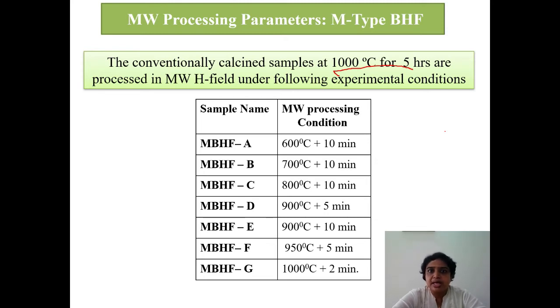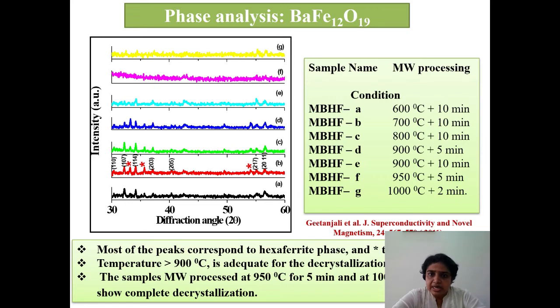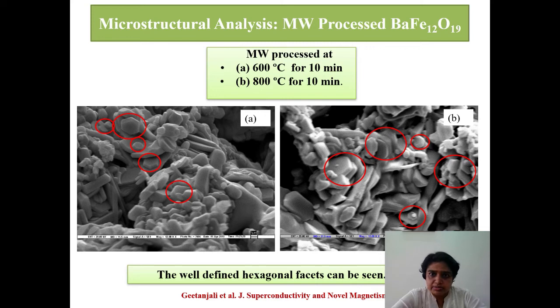We process the sample under microwave for different time and at different temperature. So what we obtain, at 1000 degrees for 2 minutes, the entire oxide structure was decrystallized. So most of the peaks disappeared now. This is the sample that is processed at 1000 degrees for 2 minutes. So the hard ferrite, barium hexaferrite, all got decrystallized within a few minutes, in 2 minutes at 1000 degrees centigrade. Then we measured its magnetic and microstructure properties.